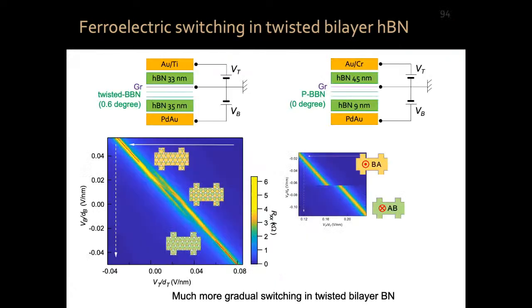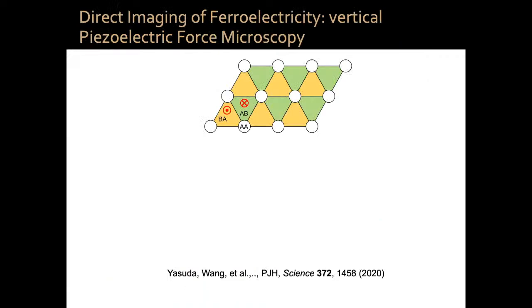So we fabricated a small twist angle, twisted bilayer boron nitride at 0.6 degrees in this case, in a similar graphene ferroelectric field effect transistor geometry. And now we can see that there is a gradual change from one resistive state to the other, as opposed to a sharp, abrupt state, because now we have this Moire ferroelectricity, which is shrinking and expanding electrically tunably. Now, do we actually have direct visualization of these AB and BA domains?